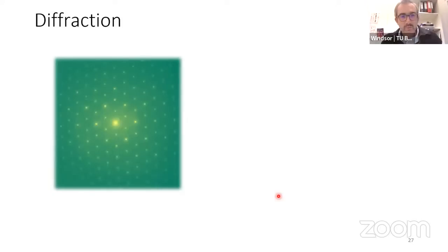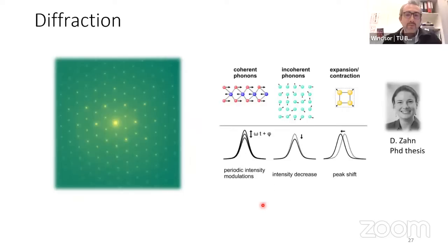So diffraction in general gives us Bragg peaks, like you just saw. And different things can happen to these Bragg peaks. This is an image taken from the PhD thesis of Daniela Zahn. One of the things you can see is intensity going up and down due to a coherent phonon. I will talk about this in more detail in a minute. And like I also said before, you can also have just a decrease in intensity on all Bragg peaks because of a growth in incoherent phonon population. And you can also imagine Bragg peaks moving around because of expansion or contraction of the lattice.